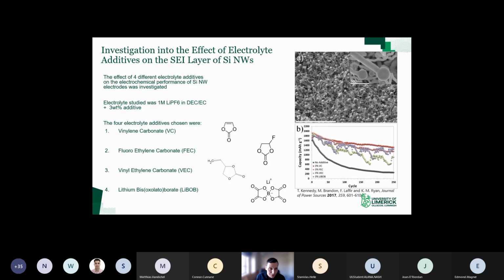So we wanted to try to stabilize that SEI layer for silicon in hopes that we could mimic the capacity retention that germanium has. So we looked at a series of electrolyte additives that stabilized that SEI layer. Typically the standard electrolyte for lithium-ion batteries is carbonate based, so you can use DEC or DMC, diethyl carbonate or dimethyl carbonate, coupled with ethylene carbonate, so they're the solvents. The salt is a 1 molar LiPF6 salt, and we added 3 weight % of each of these additives separately: vinylene carbonate, fluoroethylene carbonate, vinyl ethylene carbonate, and LiBOB, lithium bis(oxalato)borate. All of these had been used previously with graphite, and some had been used with silicon previously. So we knew they had stabilizing effects on the SEI layer.